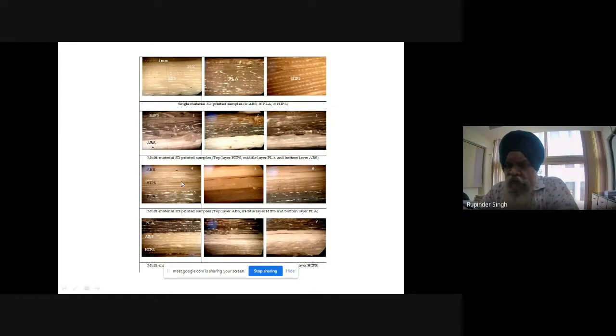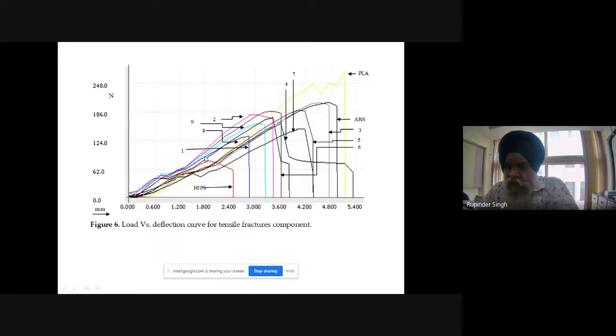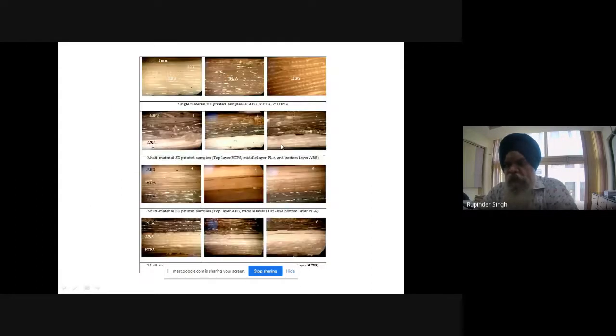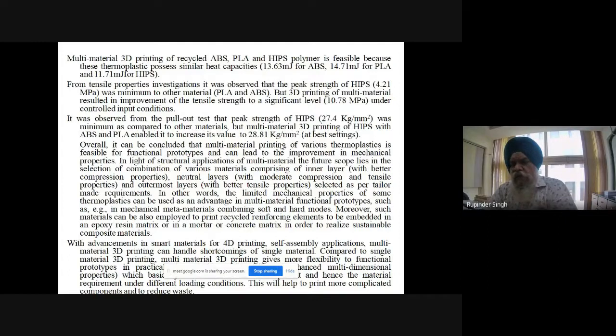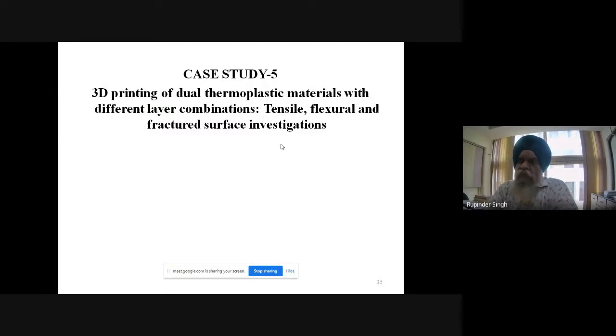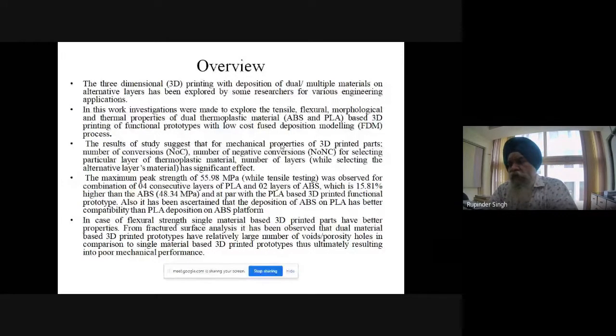Now, if you compare with figure 4, the lowest was PLA, the intermediate was HIPS, then the ABS, and there was no side flow. If I compare their mechanical properties, curve 1 has a minimum area under the curve, so it will have a minimum modulus of toughness, whereas for curve 4 the area under the curve is really large, right? So this is another important observation: which material I have to print at the top, which at the bottom, and I can select their combination. This combination is really helpful in printing some of the components. Now I'm going to tell you quickly how we will control the multi-material printing.